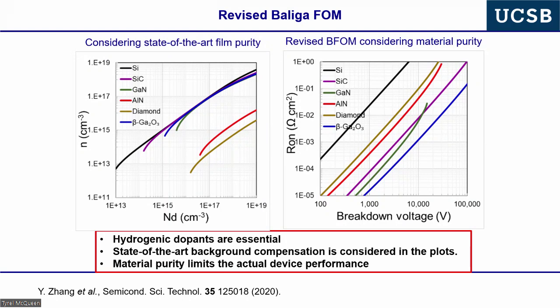When you take this factor of doping inefficiency into account and then remake these FOM plots, what you actually find is that beta gallium oxide for highest voltage is predicted to be the lowest resistance semiconductor. Okay, that's the big win for gallium oxide. So we're also very interested where germanium oxide would fall out in these analyses. Okay, and so you might start getting a feeling that these numbers really matter.